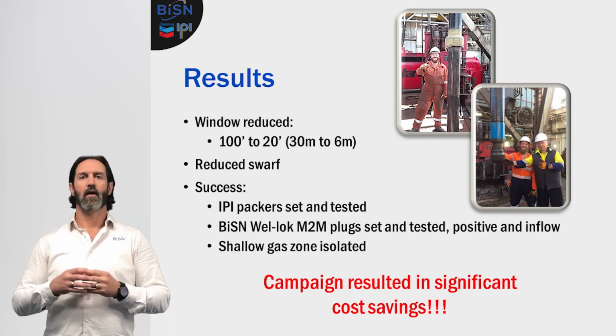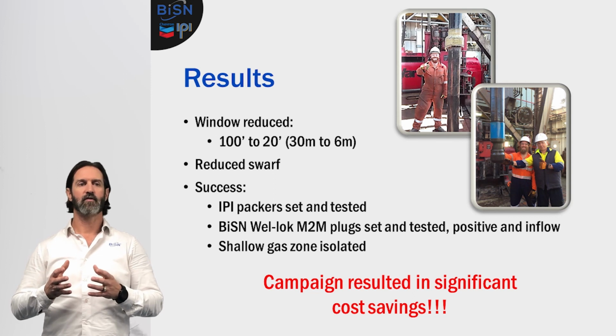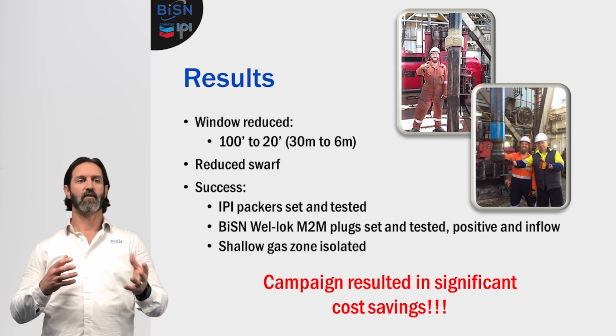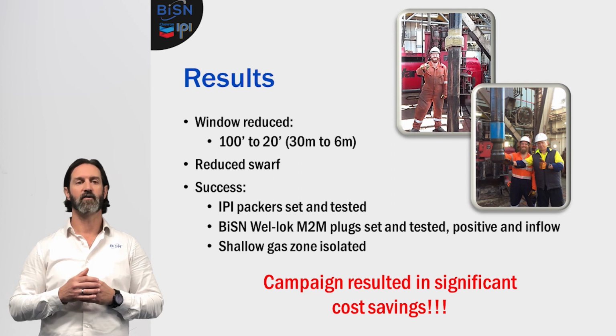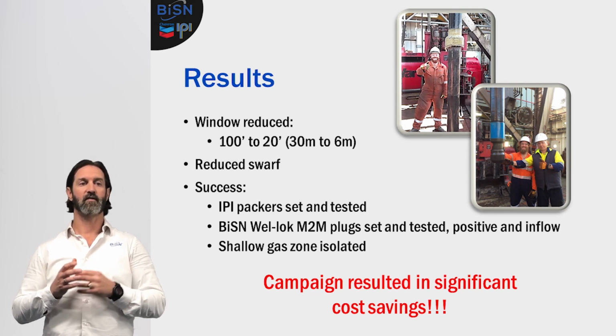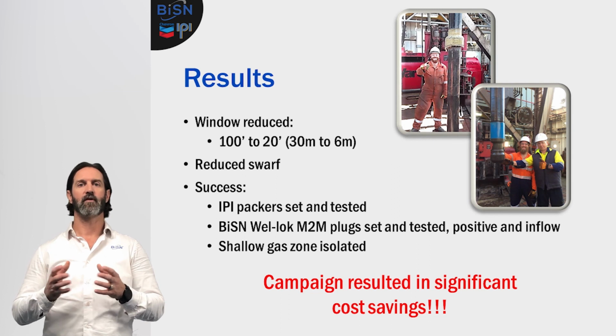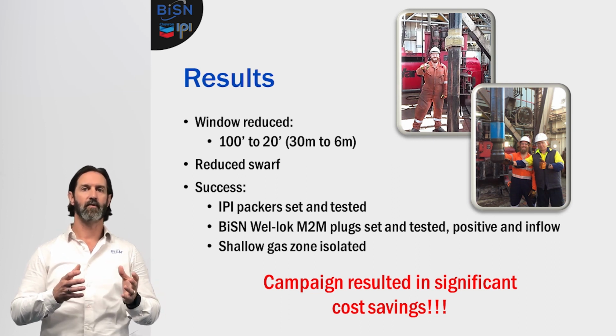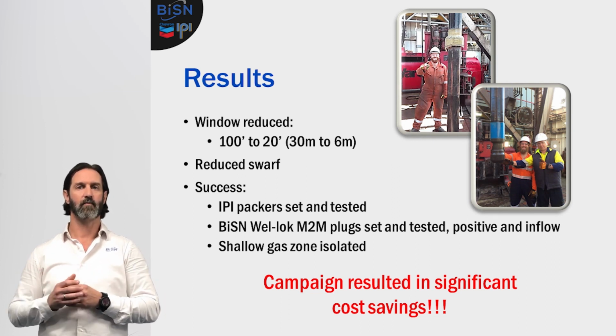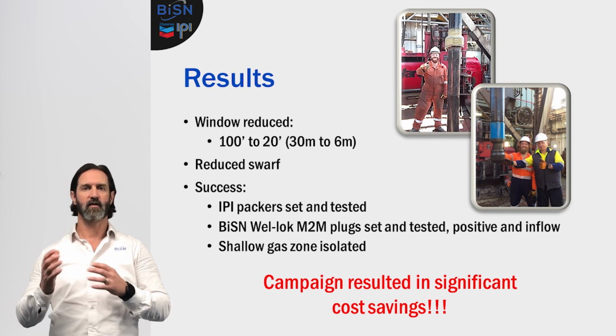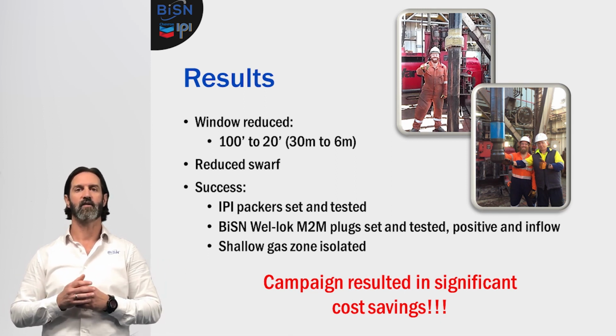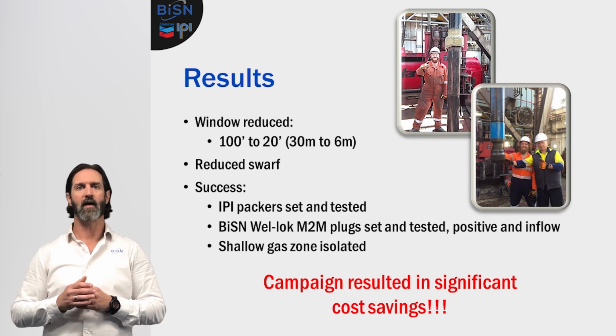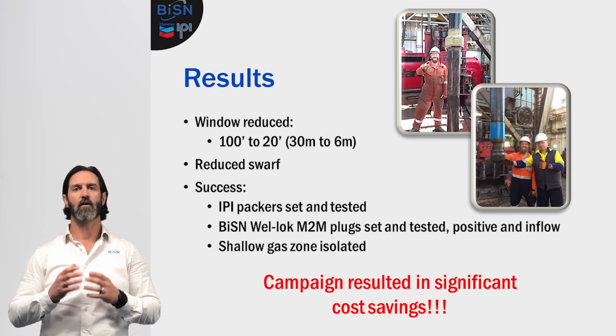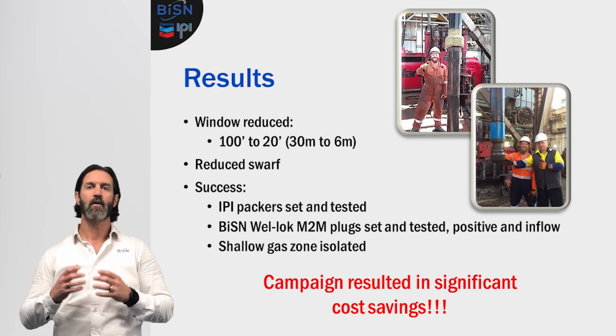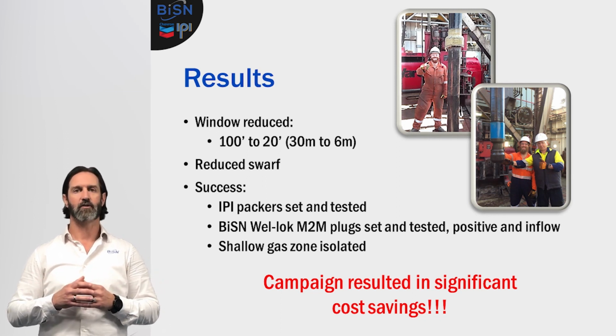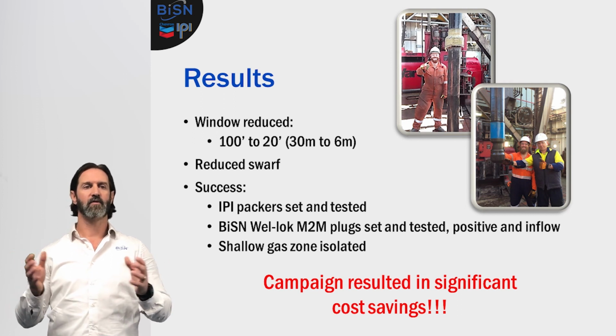So a little recap, we were able to successfully reduce the section milled windows. I did not mention this earlier, but we reduced them from 100 feet down to 20 feet. That's 30 meters down to 6 meters. The reason we were able to shorten it so much is that instead of a 30-meter cement plug, we only needed a 1.5 meter bismuth alloy plug. And again, this is an acceptable practice, as was accepted on a recent campaign in Norway by the PSA, Petroleum Safety Authority, according to the NORSOK D-010 standards. So significant reduction in swarf by shortening that window. And overall, it was a big success.